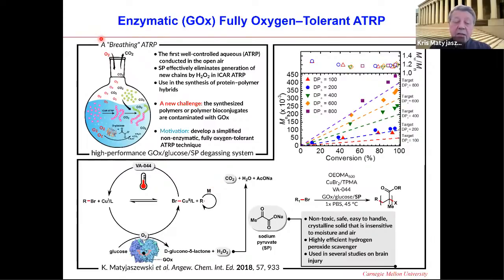And this breathing cycle essentially is based on oxygen diffusing in and carbon dioxide getting out. It is like a classical breathing process. And now you could see that the molar masses predicted and the molar masses measured are in very good agreement, and we do not generate new chains. However, there is a challenge. There is still glucose oxidase in the reaction mixture. Can we somehow remove it or get rid of it?